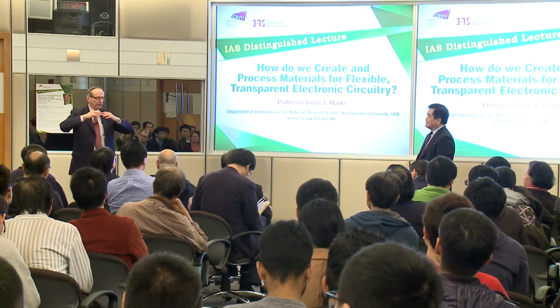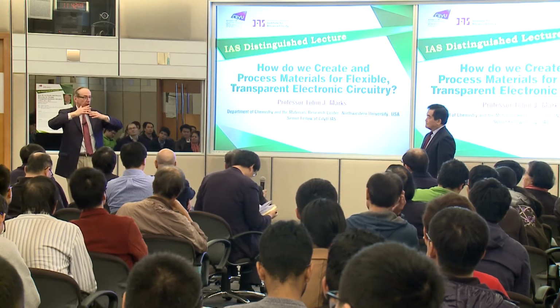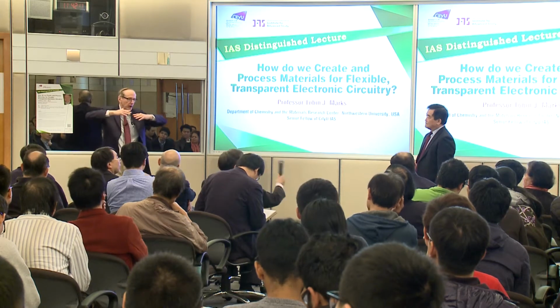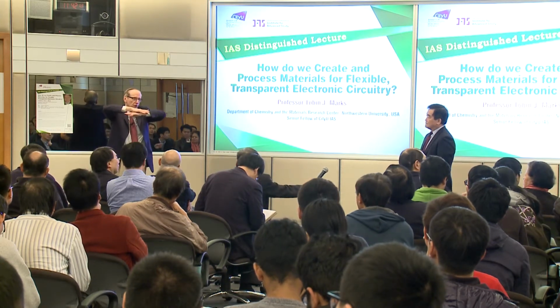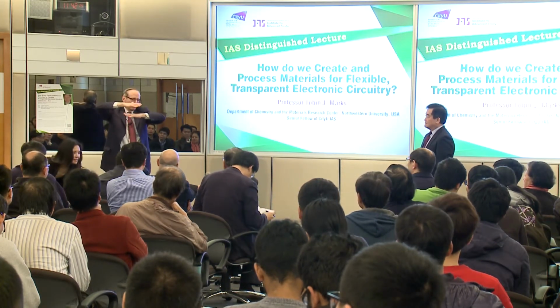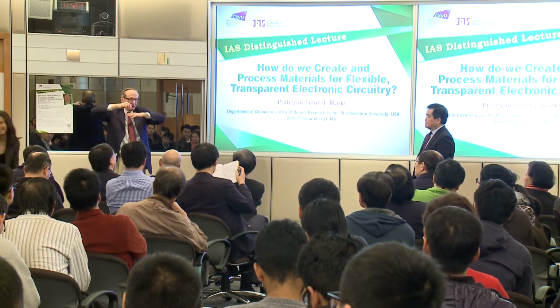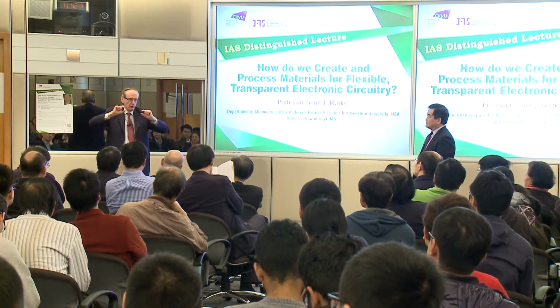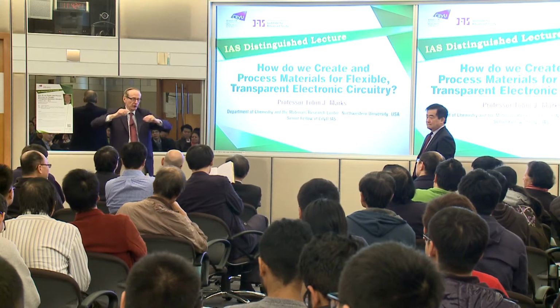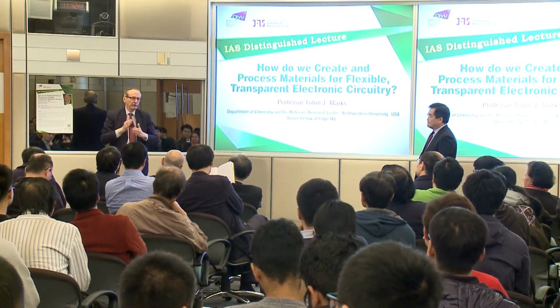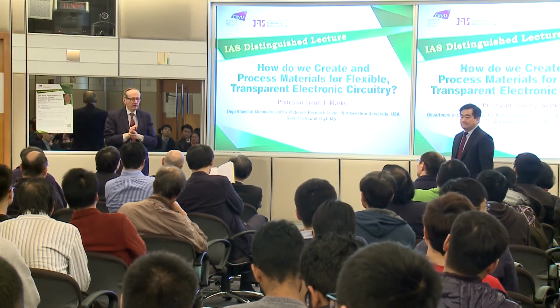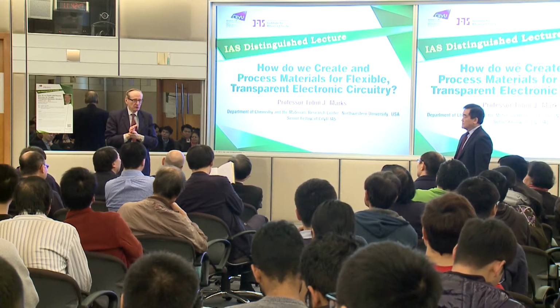Okay. So first of all, you're right. It's amorphous. And the other thing, the way the engineering is done, for the layer under it or the layer above it, you don't have 100% contact. You only have certain places where it contacts. And that turns out to relieve some of the stress. The key point is that it didn't crack.